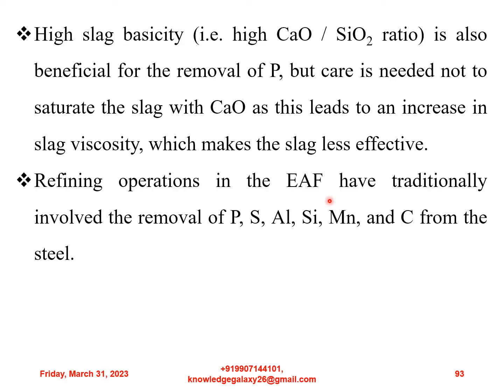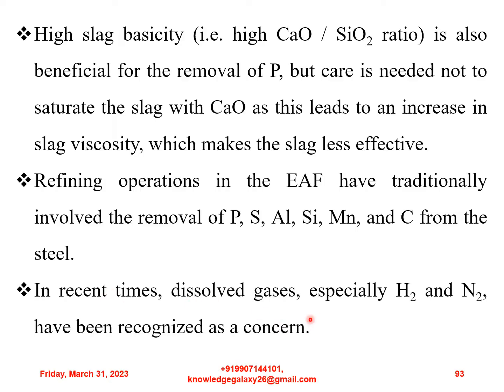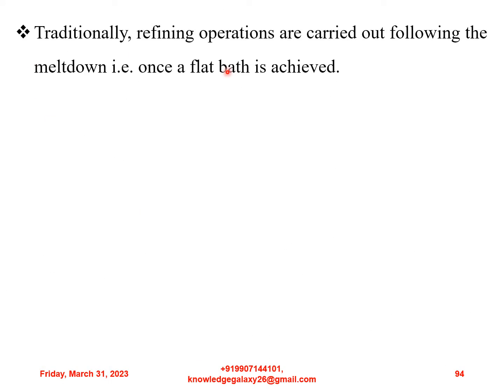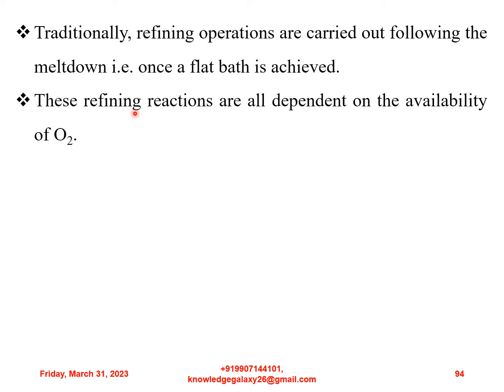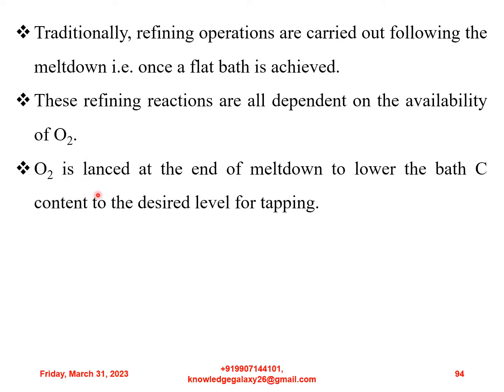Refining operations in the electric arc furnace have traditionally involved the removal of phosphorus, sulfur, aluminium, silicon, manganese and carbon from the steel. In recent times, dissolved gases, especially hydrogen and nitrogen, have been recognized as a concern. Traditionally, refining operations are carried out following the meltdown, that is, once a flat bath is achieved. These refining reactions are all dependent on the availability of oxygen. Oxygen is lanced at the end of meltdown to lower the bath carbon content to the desired level for tapping.